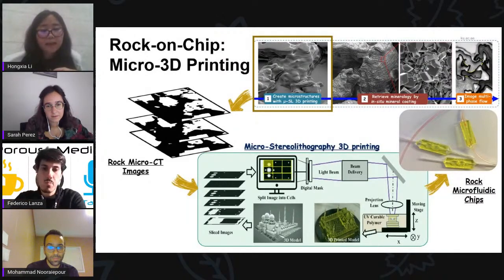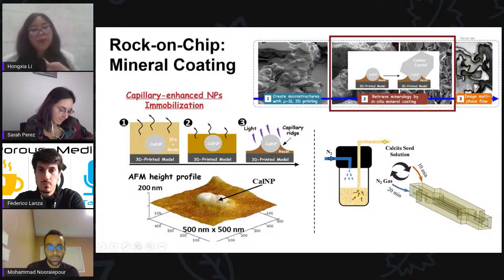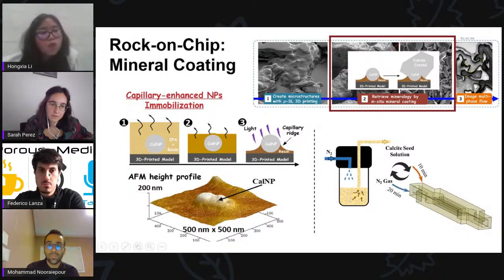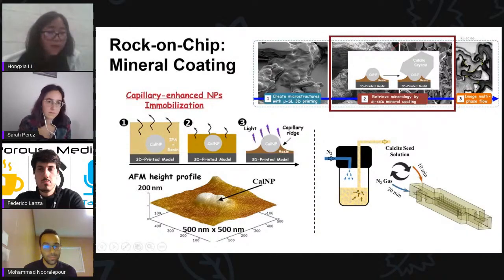But again, we printed with a polymer resin, so it's far from the rock which we want to research. To solve this problem, we did one thing called mineral coating. To do the coating is actually a little bit complicated. First we need to plant the seeds, a calcite nanoparticle, on the surface. With this seed, we can further grow a crystal that mimics our rock, because if we observe the rock surface, it is made of mineral crystals. So the first step is to fix this seed, the nanoparticle, on the rock surface.